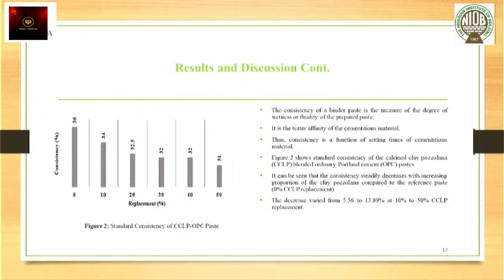And it can be observed that the consistency steadily decreases with increasing proportion of the clay pozzolana compared to the reference paste, which is the 0% addition of clay pozzolana. The replacement levels were at 10% replacement of the pozzolana by weight of the ordinary Portland cement, 20%, 30%, 40%, and 50% respectively. The decrease varied from 5.56 to 13.89%, at 10% to 50% calcined clay pozzolana replacement. The next slide, please.